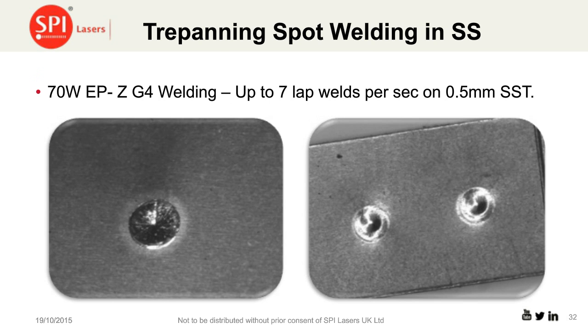So trepanning spot welding, that's one of the big things. We can actually control the size of the spot by trepanning it and control the heat input quite nicely. And this is an application where we were welding 0.5 millimeter stainless steel, and we were getting up to 7 lap welds per second using just a 70 watt laser.